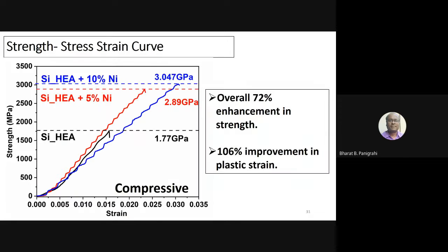The interesting thing comes in their strength. You can see that this particular high entropy alloy, which is the black line, has a strength of 1.8 gigapascal. I'm talking about 1700 megapascal strength. You can imagine 1700 megapascal is very high strength. But if you add 5% of nickel, we are able to jump the strength to almost close to 3. By having 10% of nickel, we have crossed the strength to 3 gigapascal, 3000 megapascal strength.